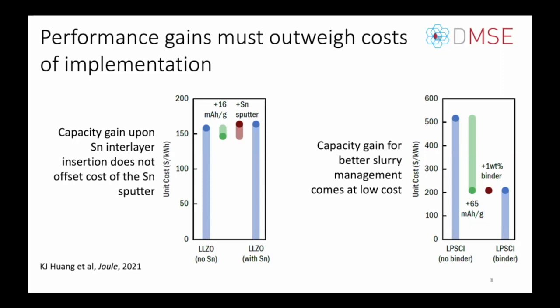But in this case, the cost of the deposited layer has an equivalent cost that essentially outweighs the performance gains. So that's the left-hand side, where the green is shown as the improvements in performance, lowering the dollars per kilowatt hour, but then as a trade-off, there are increased costs associated with sputtering the tin. And obviously the performance at scale, we don't have the direct measurement of, and we have modeled what the tin sputtering would cost at scale. But just this idea that there is maybe a challenge in having those performance gains outweigh the cost of implementation is a flag for us to think more thoroughly about in the design of that particular research or pursuit of that particular direction.